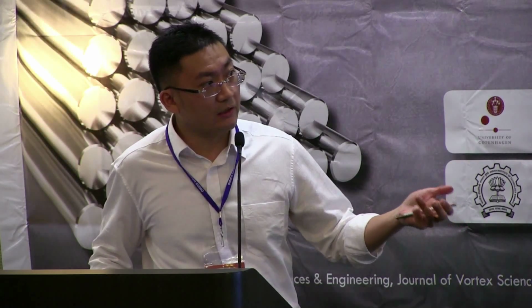And from the XRF, we can see the material loading. So we use the XRF to analyze the metal weight percentage. So you can see with less platinum, we get less weight percentage loading. 9 point something is reasonable, because if you have more loading, the performance will be better, but 10 is roughly it for the characterizations. Because of different molar ratio, the size is decreased due to the nucleation rate of platinum in the composite, in the alloy.